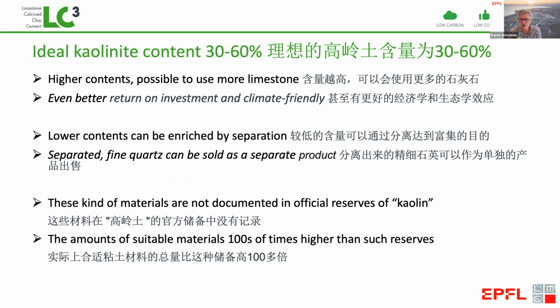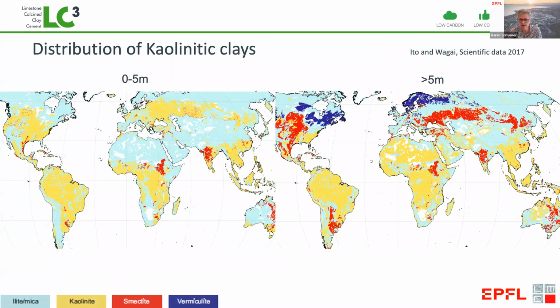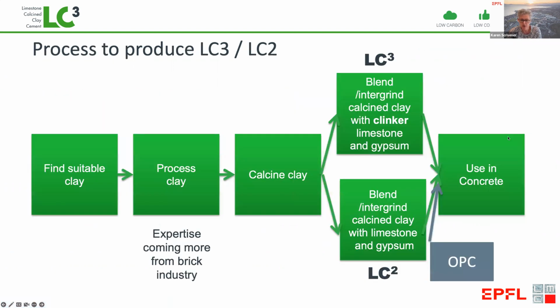But the important point here is these kind of low-grade kaolins are not documented in official reserves. The amounts available are many orders of magnitude more than high-grade kaolin for ceramic applications. And we can get an idea of the distribution by looking at these maps, because everywhere in either of these maps you see this orange-yellow color, you will have clays containing kaolin. And you can see in China, they're almost everywhere, apart from really maybe the very far north.